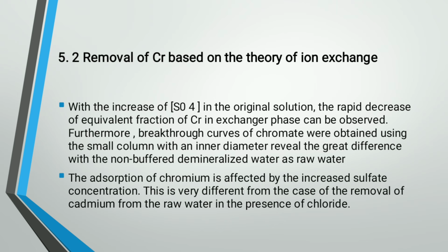Followed by the next result, removal of chromium based on the theory of ion exchange. With the increase of SO4 in the original solution, a rapid decrease of the equivalent fraction of Cr in the exchanger phase can be observed. Furthermore, breakthrough curves of chromate were obtained using the small column with an inner diameter, and revealed a great difference with non-buffered demineralized water as raw water. The adsorption of chromium is affected by the increased sulfate concentration. This is very different from the case of removal of cadmium from water in the presence of chloride.